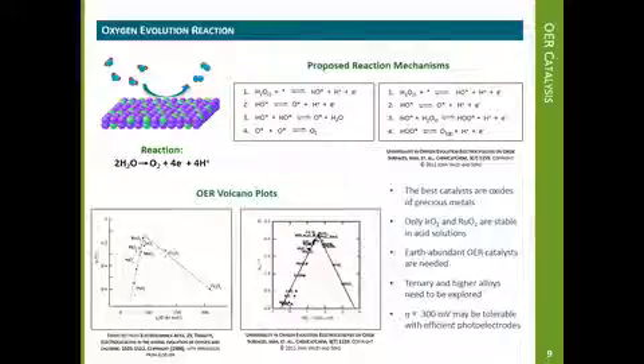The best catalysts, which are found at the apex of these plots, are oxides of precious metals. Only iridium oxide and ruthenium oxide are stable in acid. Thus, the need to discover Earth-abundant OER catalysts, perhaps in the form of ternary and higher-order alloys, remains a challenge.